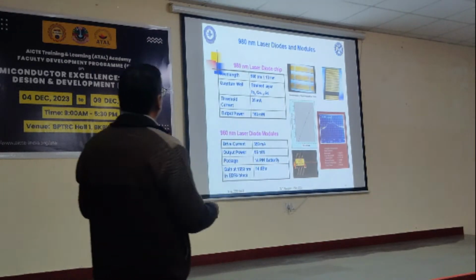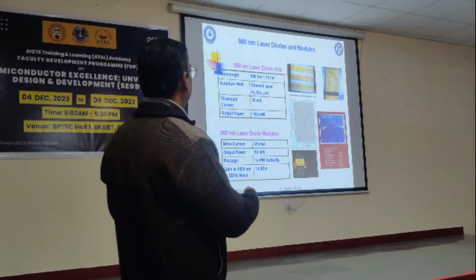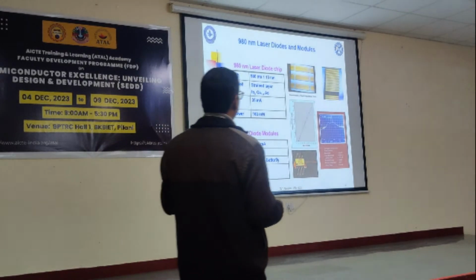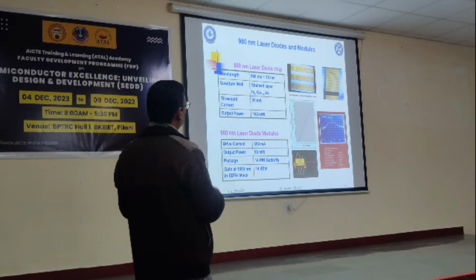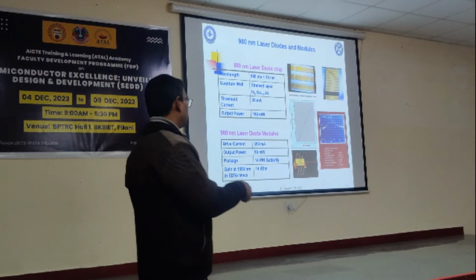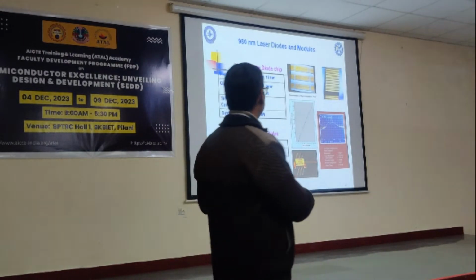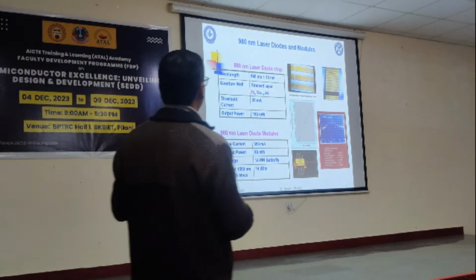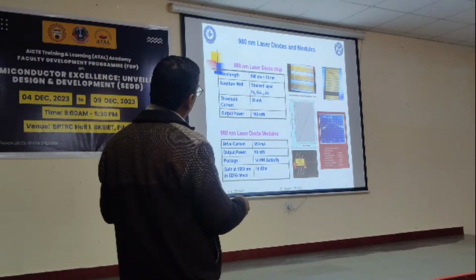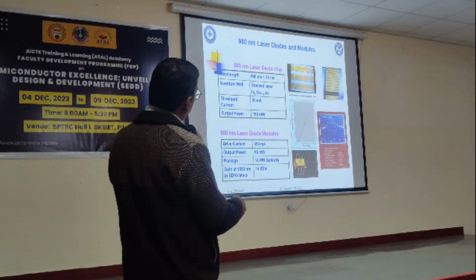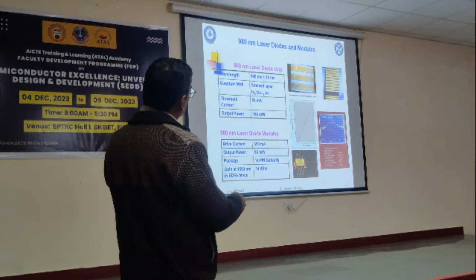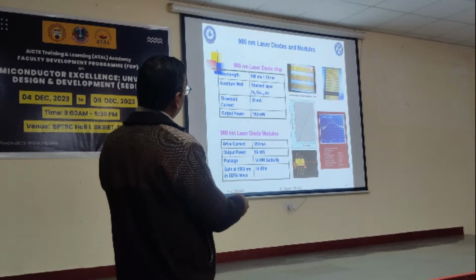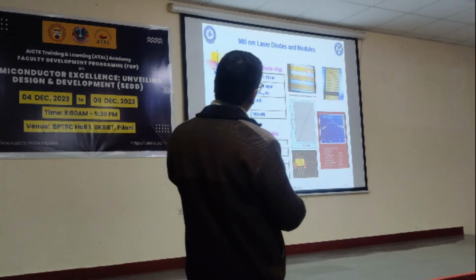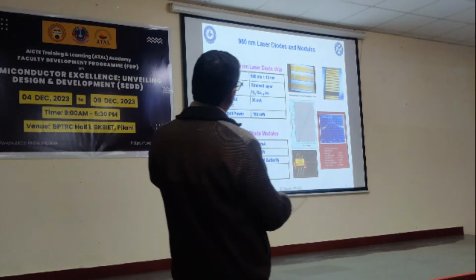So this is another device. We have also fabricated a 980 nanometer laser on indium gallium arsenide. That is for another application. It is also another semiconductor, a ternary semiconductor. This is the individual laser chip. This is the length, and on one side we have to go for a high reflection coating. On the other side we have to go for a low reflection coating, so that the emission will be from the low reflective coating side.